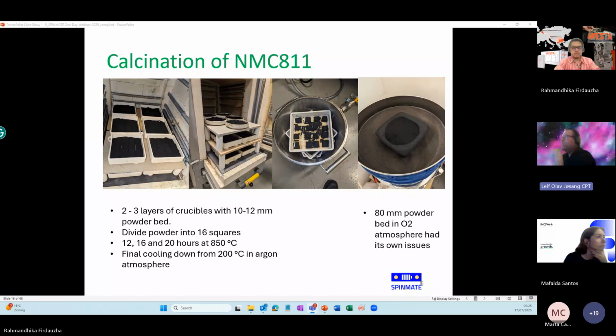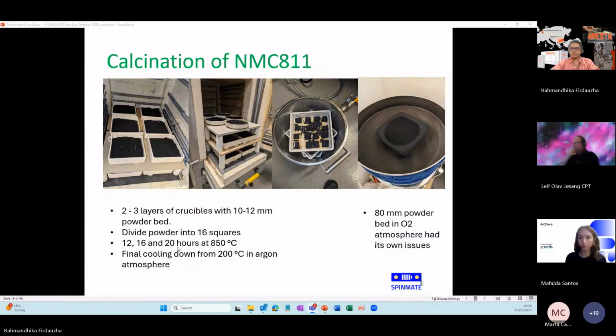After calcination, I removed the crucibles from the furnace at between 200 and 150 degrees and placed them under an argon blanket to minimize the effect of moisture and CO2 from the air. We used 12, 16, and 20 hours of calcination at 850 degrees. And we had the best results with 20 hours. I think we can move on to the next step in the process.